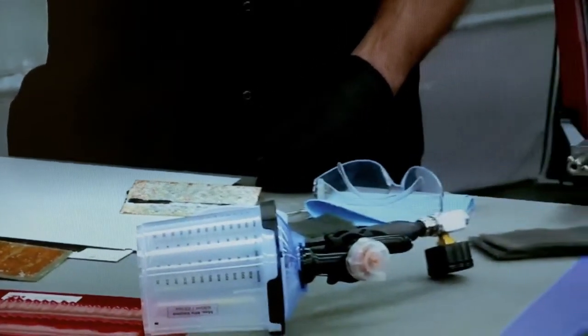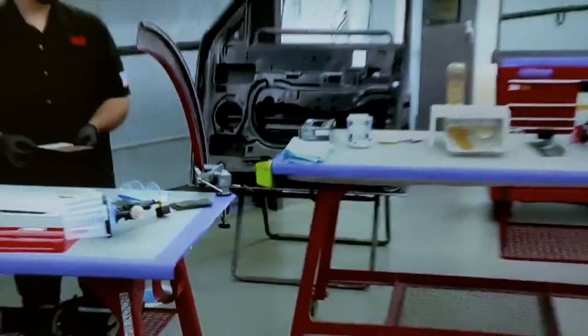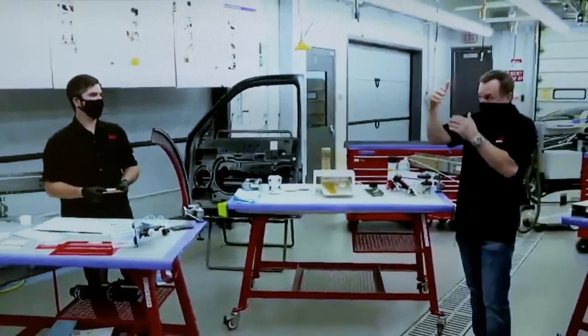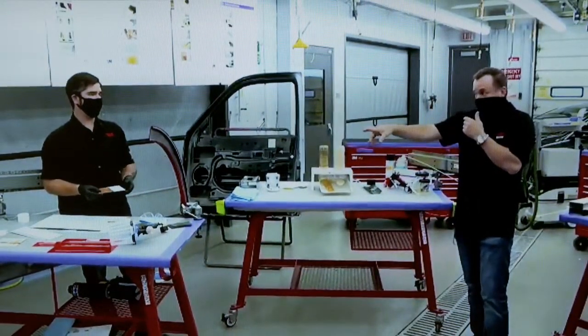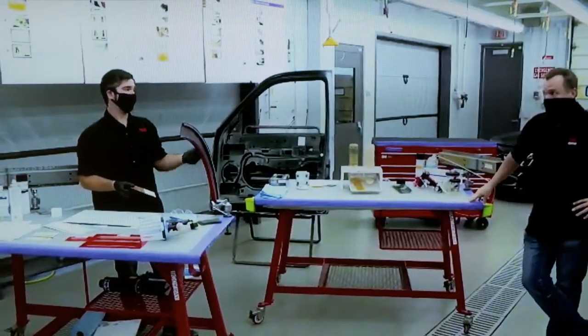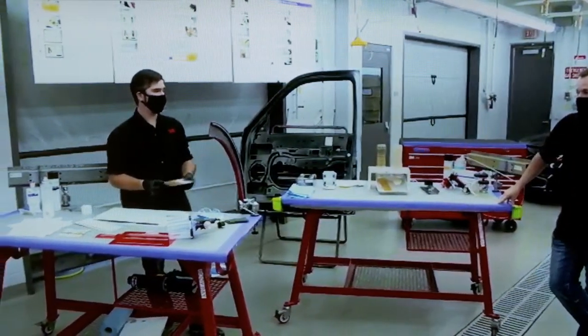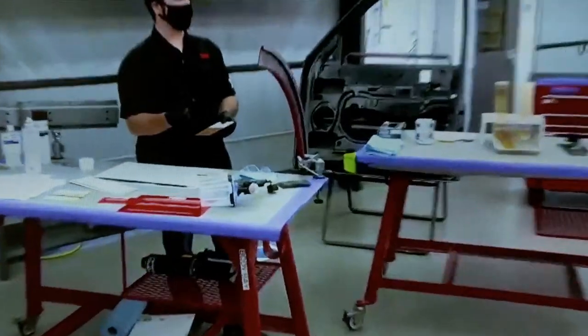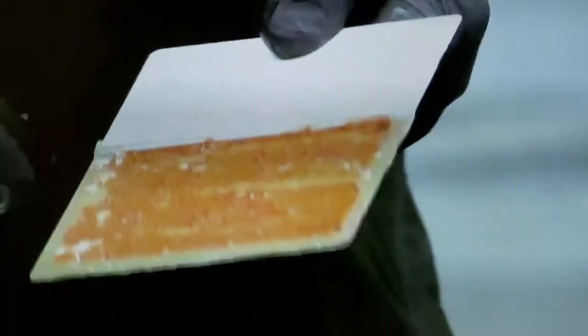The other thing I like is when you do your testing on those, you dip the edges in wax. I just saw another brand show some testing they did. You could see rust on there, but you could tell it started on the unprotected edge, then moved down and ran onto the sample. That's called corrosion creep, and there's actually an ASTM test for that. So they basically contaminated one test with another by doing that. You're right: when you're doing a B117 test, you want to make sure the edges are protected. In this case, we dip these in wax after they're built, and then put them in the chamber, so we have no corrosion creep coming in from any edge.